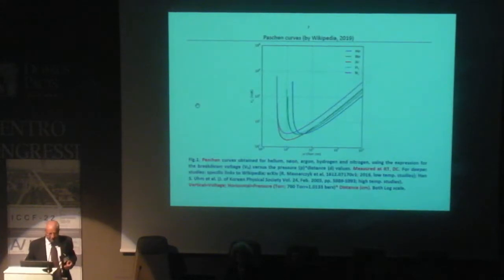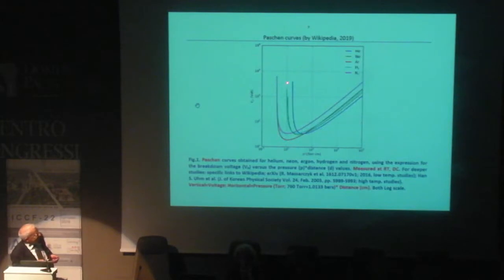Okay. This is the quite famous Paschen's law. This is the product between pressure and distance, anode to cathode. It is the voltage necessary to have conduction. So reducing pressure, with the distance constant, the voltage is lower, and then it starts rising again. So this minimum is the operating point. It means if we have larger voltage, we can work at a larger pressure. Quite simple. This data was made in DC condition at room temperature. They made some other studies at low temperature and high temperature. Usually at high temperature we have some advantage.